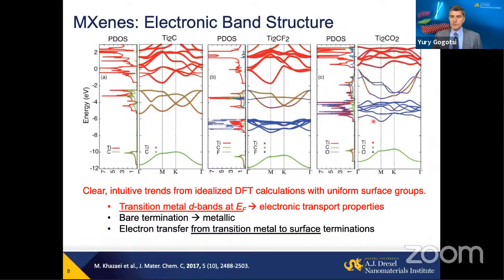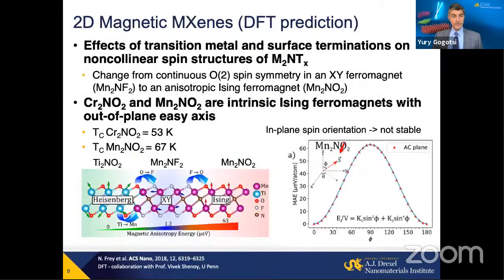So what is important? We have metals where, by changing the surface termination, we actually tune the Fermi level. So there are metals which are two-dimensional, water-soluble, and with a tunable Fermi level. And we can do it reversibly, chemically or electrochemically, for example, by injecting charges here.